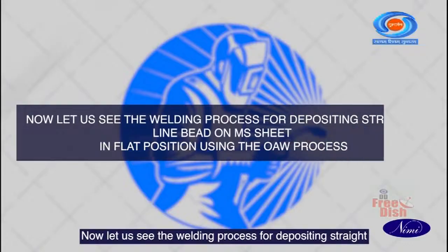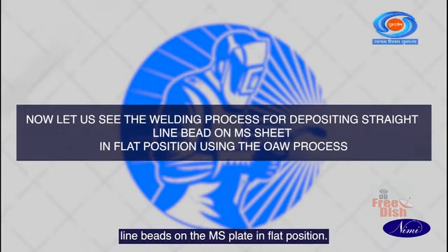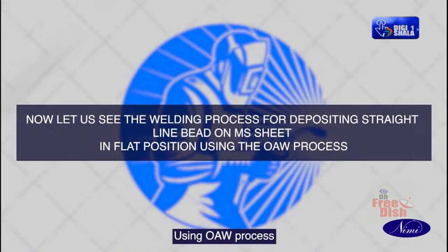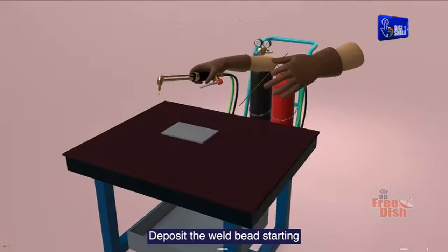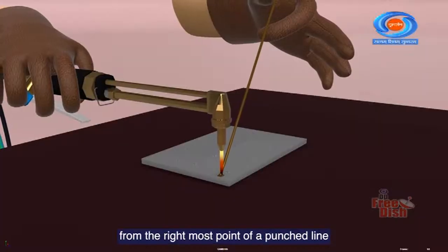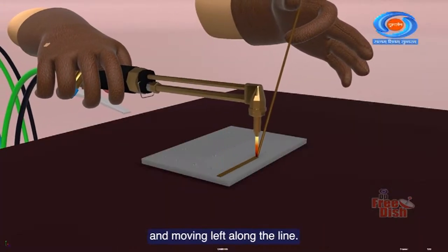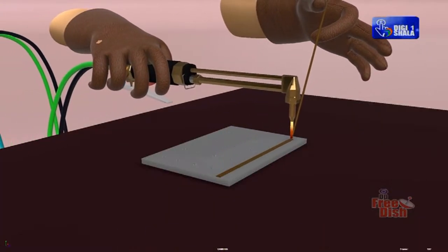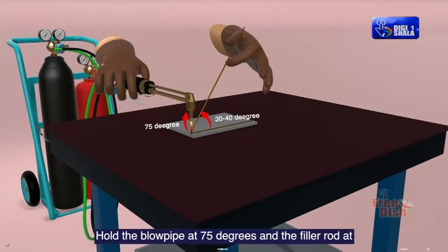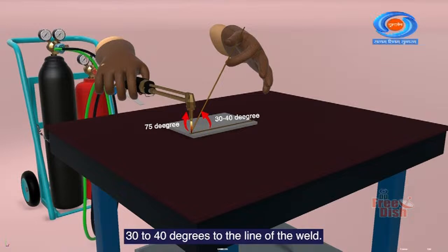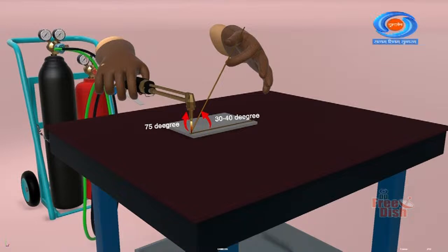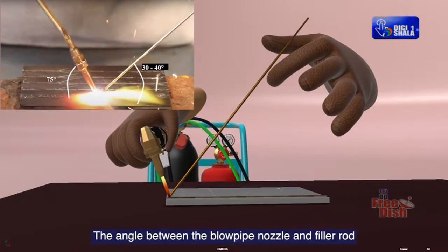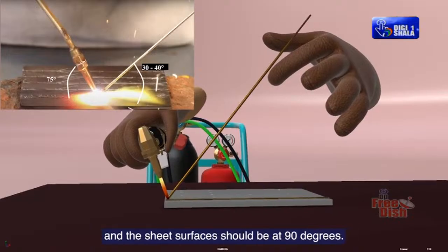Now let us see the welding process for depositing straight line beads on the MS sheet in flat position using OAW process. Deposit the weld bead starting from the rightmost point of a punched line and moving left along the line. Hold the blowpipe at 75 degrees and the filler rod at 30 to 40 degrees to the line of the weld. The angle between the blowpipe nozzle and filler rod and the sheet surfaces should be at 90 degrees.